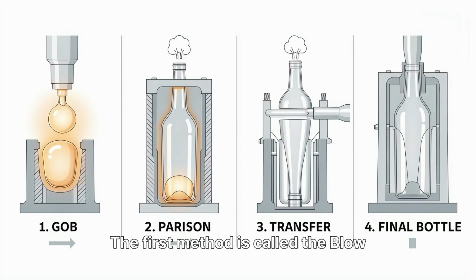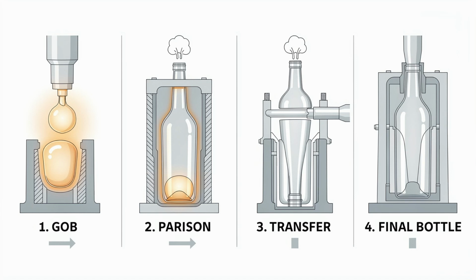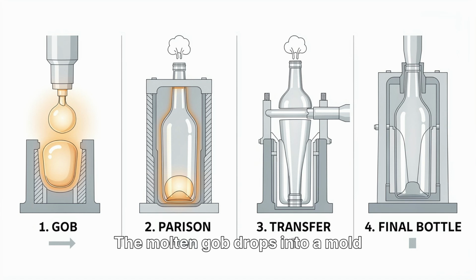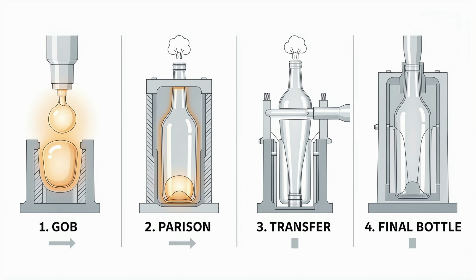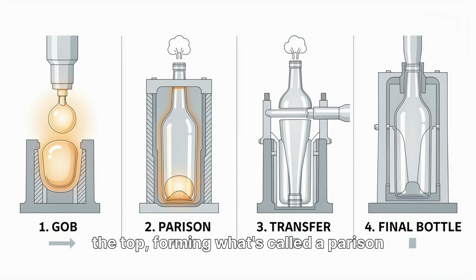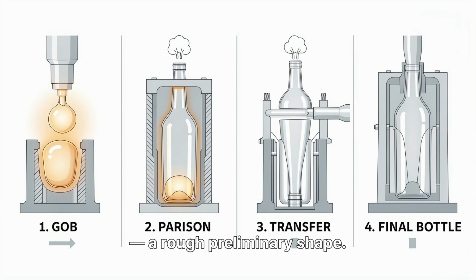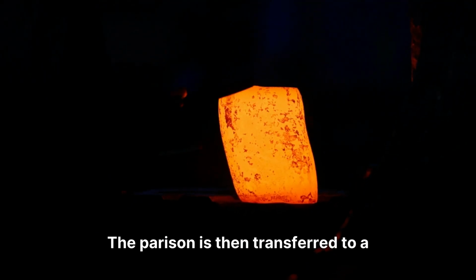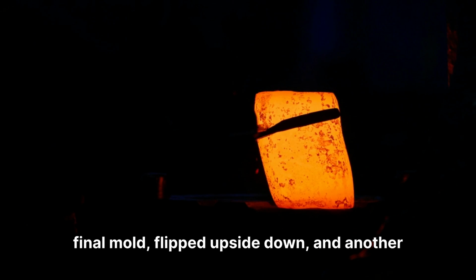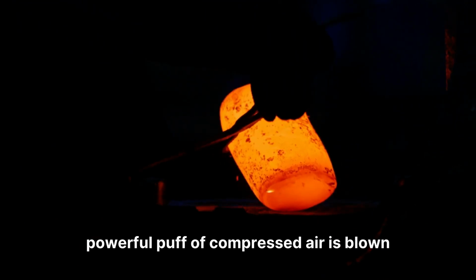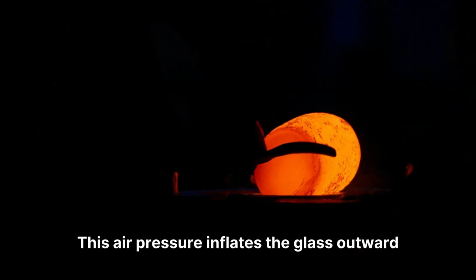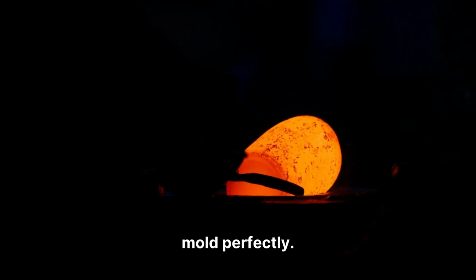The first method is called the blow and blow process. The molten gob drops into a mold called a blank mold. A puff of compressed air blows into the top, forming what's called a parison, a rough preliminary shape. The parison is then transferred to a final mold, flipped upside down, and another powerful puff of compressed air is blown into it from below. This air pressure inflates the glass outward until it fills every contour of the mold perfectly.